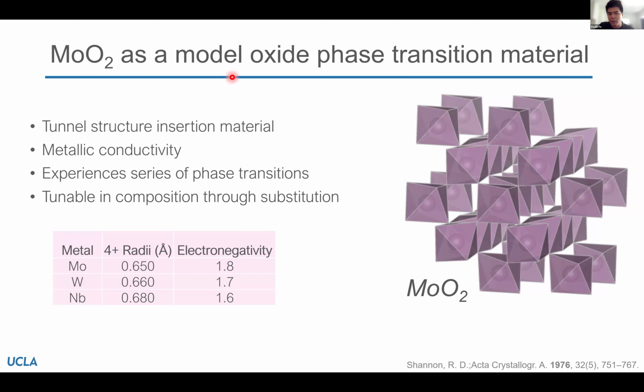And so going back to our requirements for fast lithium ion charging and discharging, looking at the structure here, there are tunnels, which are one of the preferred motifs for lithium diffusion. So lithium can travel through these tunnels and reach the molybdenum in a quick way to facilitate that lithiation reaction, that reduction reaction of our molybdenum. And it also has good electrical conductivity. So those are two of our requirements for fast charging. What it does experience, however, is a series of phase transitions, which again, I mentioned can be rate limiting.